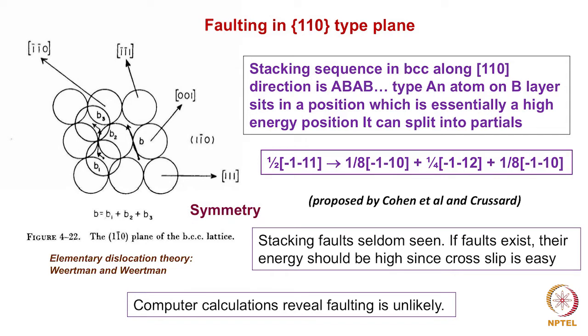So this itself can be represented by the vector of the perfect dislocation splitting into 3 dislocations, one with 1/8 [1 1bar 0], another with 1/4 [1bar 1bar 2], then plus 1/8 [1 1bar 0]. This sort of reaction has been proposed by Cohen and Crussard. But when people looked at it, the Burgers vectors of these dislocations are not the translation vectors in the BCC lattice.